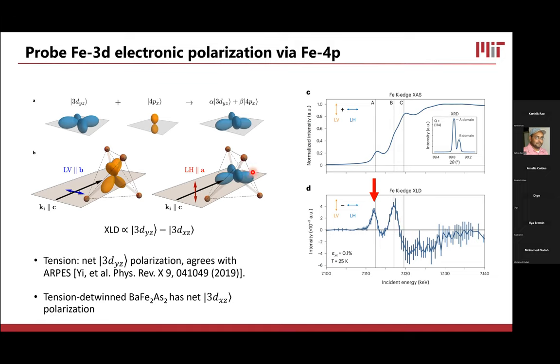Right, but now, if we focus on this A peak, we can put together a model that looks like this. Since this is a K edge absorption, we are talking about moving an electron from the 1s into the iron 4p orbital. That is not a direct probe of the iron 3d orbitals. But the 4p and the 3d orbitals have some hybridization, which allows us to measure the polarization of the 3d orbitals by looking at the polarization of the 4p orbitals, basically. You can go through our supplement and see what we worked through to arrive at this. But this is essentially the basis of how we're able to probe the 3d orbitals. And this isn't uncommon. We do this in hard X-ray XMCD for magnetic order all the time as well.